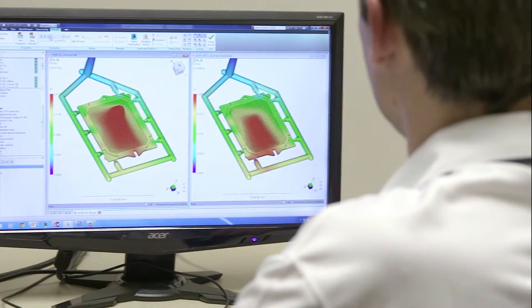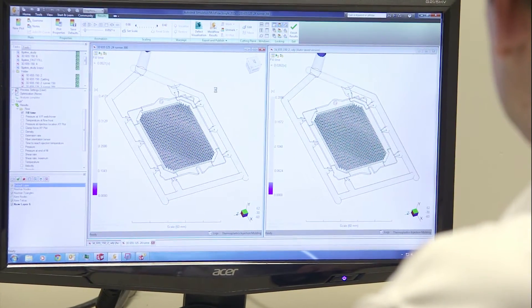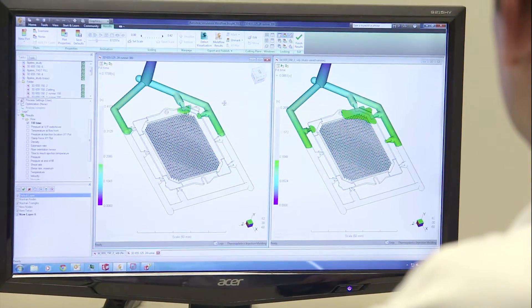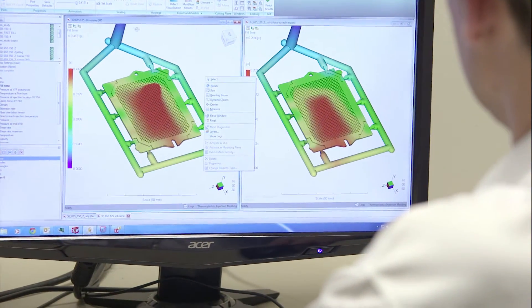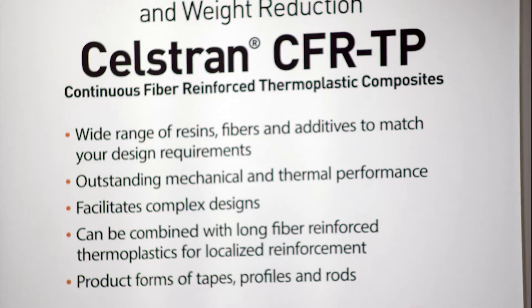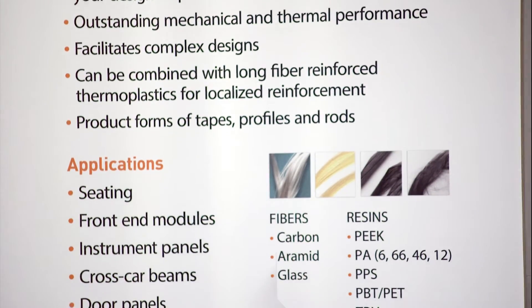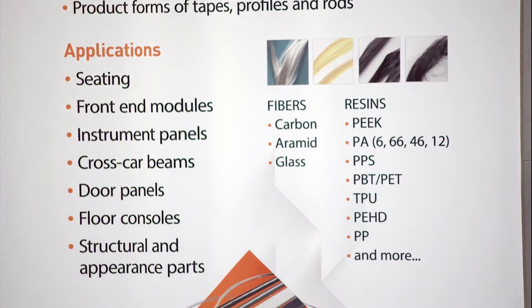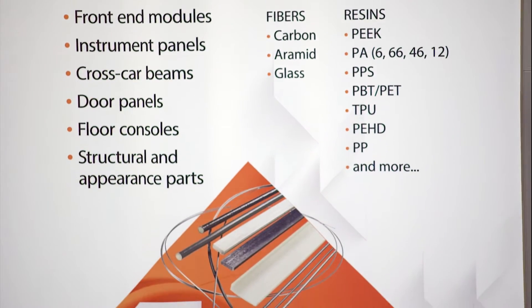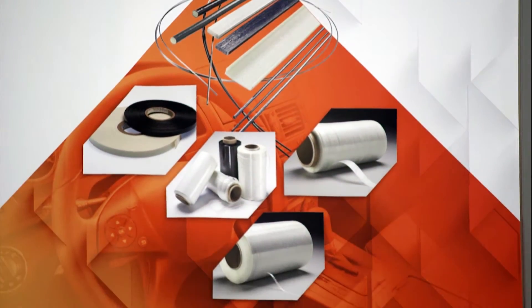Celanese has a fairly broad portfolio. When you think about weight, you think about metal substitution — how do I take something that was in steel originally or even aluminum and drive that weight down? We do that with our long fiber technology, which is usually either a glass fiber with a polypropylene matrix or nylon matrix holding it together, or what we're starting to see a lot more of is carbon fiber reinforced materials, because that's really taking a lot of mass out and providing a lot more stiffness, but there's a cost trade-off so you have to think about that.